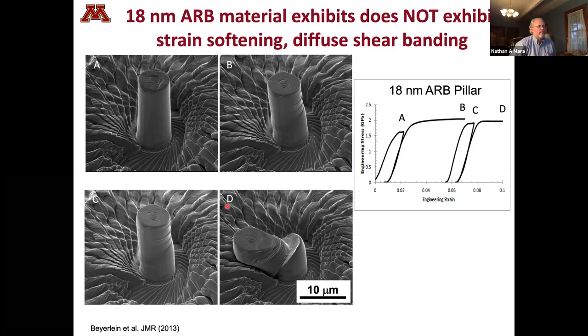During this process, what you notice is we don't get this nice single shear band anymore like we had in the PVD case. We get what's called diffuse shear banding, where we have multiple shear bands going across the material that then eventually just lead to failure. So sure, it's a very strong material, 2 GPa flow stress here, but not particularly deformable.